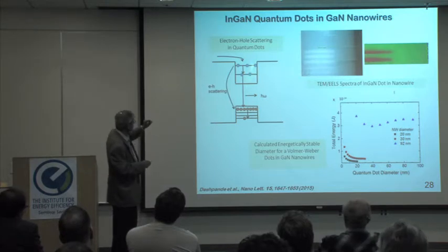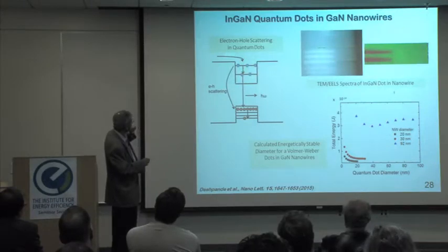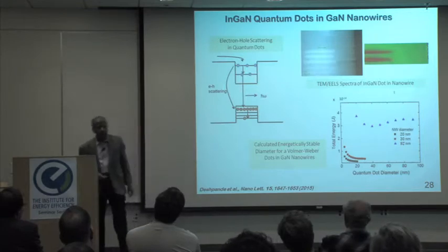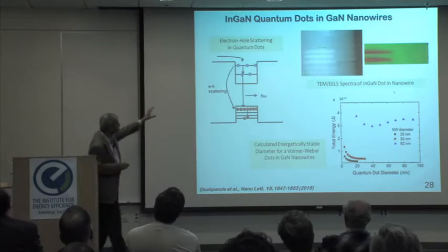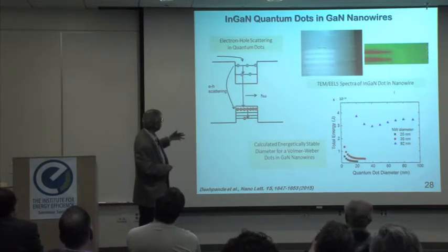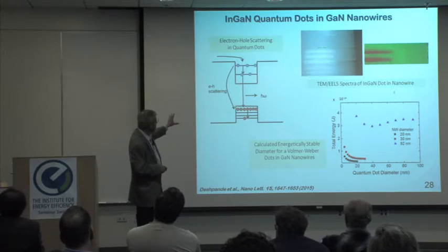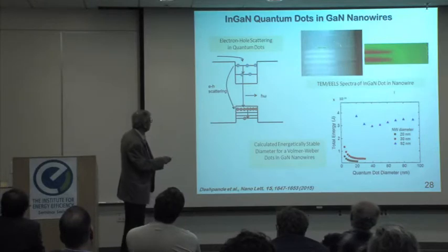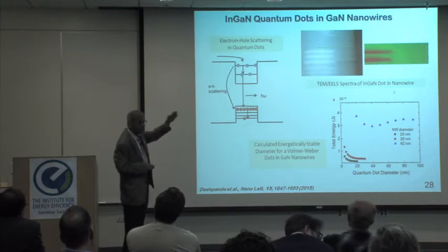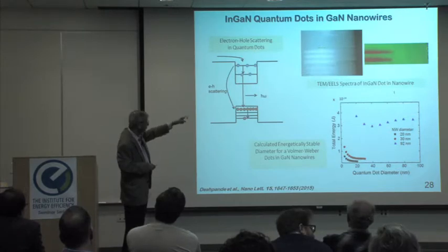Now this is with the assumption that this energy difference is larger than the phonon energy, of that order, tens of milli-electron volts. But it doesn't matter. Even if the electrons are here in the continuum, where they probably are, you would have that bottleneck. In the indium arsenide system, this is very well understood. But at this point, it is just an explanation. However, this is the only way to explain all the results. And there is no doubt that we need this to explain the increasing radiative lifetime with temperature in this system, and we know that we are forming a dot.